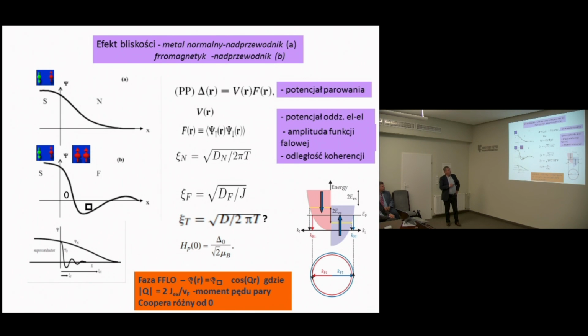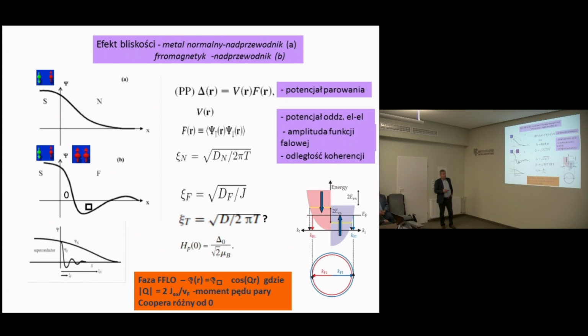Then in the normal metal we have a non-zero vector potential, pair potential, in the normal metal, and this effect is long range. It can occur up to 1 micron or even more. And quite a different story is if we have a ferromagnet in contact with the superconductor. First of all, of course, if the exchange field is very large, I mean, generally the Curie temperature is much larger than the critical temperature, then the superconducting state will be suppressed. And this is the so-called, as I mentioned earlier, paramagnetic limit. So this means that the exchange field is breaking the Cooper pair.